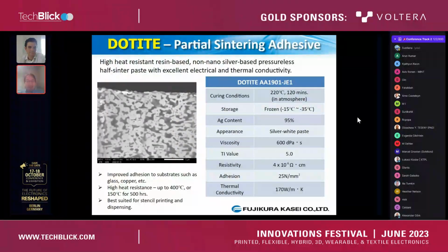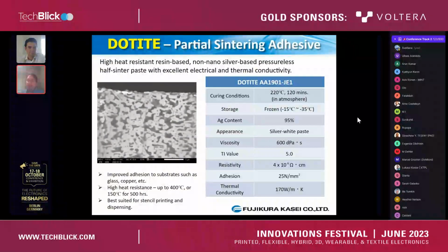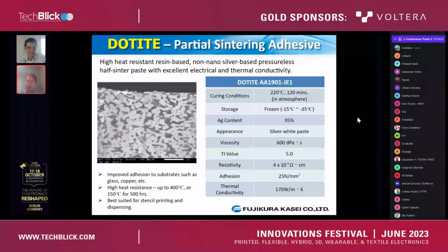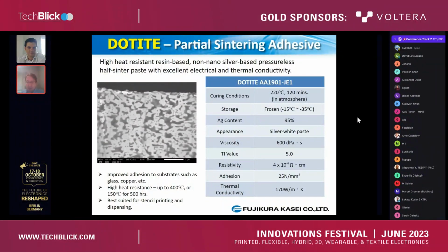AA1901JE1 is a 95% silver, non-nano, half-sintering paste designed with a high heat-resistant resin as a pressureless sintering adhesive. The additional adhesion from the resin allows it to be used in a wider variety of substrates, such as glass and copper. This gives it